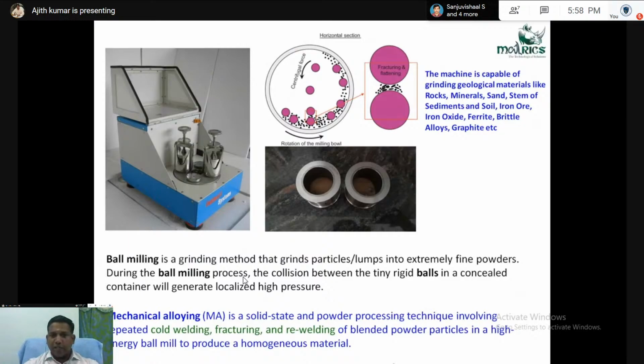In the powder metallurgy process, one of the important steps to make an alloy, that is, solid state alloying, is ball milling. Ball milling is a grinding method that grinds particles or lumps into extremely fine powder. During the ball milling process, the collision between the tiny rigid balls in a sealed container will generate localized high pressure. So, mechanical alloying. We already discussed alloying. Alloying means mixing two metal elements and making a new alloy.